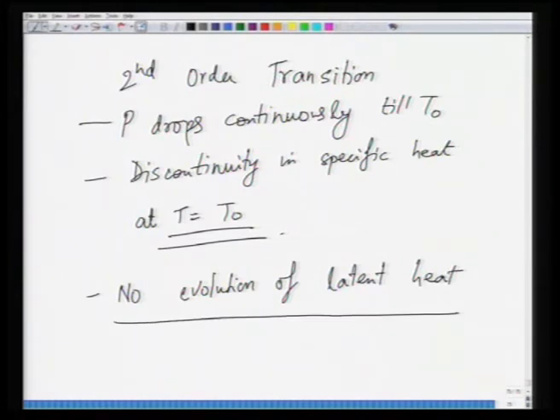If there is no evolution of latent heat, it means that when the material is going from one state to another, there is not massive reconstruction taking place. So the transition is rather not destructive in nature. It's not like the liquid to solid transition where you have evolution or absorption of heat depending upon whether you cool or heat. Rather, it's a transition where you have a change in specific heat, a discontinuity in the specific heat at the transition, but no evolution of latent heat. So in that sense it is not a destructive transition.